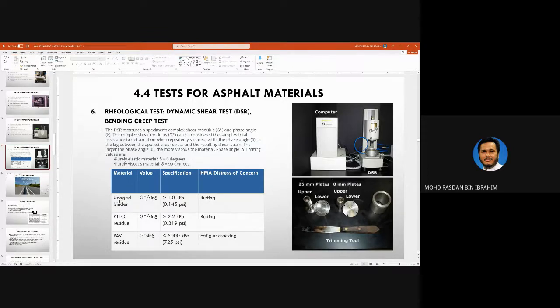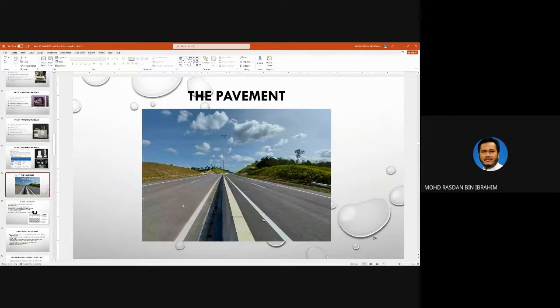So unaged binder, meaning that your sample, you use fresh bitumen, and then you test it and measure the value for G star over sin delta. So if the value is more than 1 kPa, that bitumen is suitable to resist rutting. I'll explain to you next week what rutting is. Rutting is when you see on the surface of the road, let's say here, the surface here is very flat, nice and flat. But for older pavement, you can see on the wheel track here, it will have indentation, as if the tires have caused the pavement to deflect only at the tire path. So that is rutting.